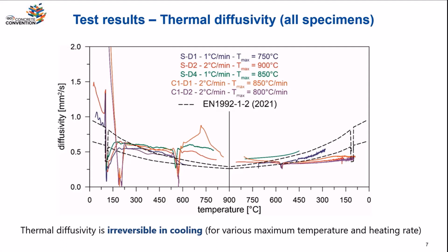Basically, the curves are almost horizontal. So it means that those thermal properties, they are not recovered. They keep the values that they had at the maximum reached temperature. So that's important in simulations. If you want to capture the continued heat transfer during cooling, part of the section at the periphery will be cooling, and we have to use the right thermal conductivity and so on.